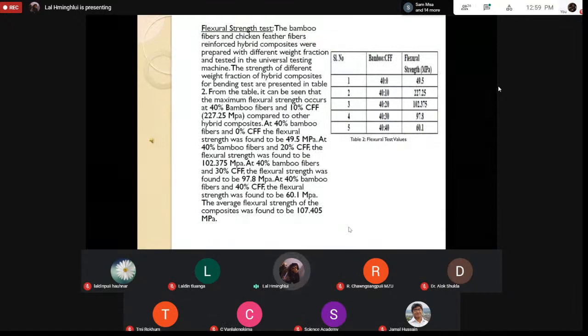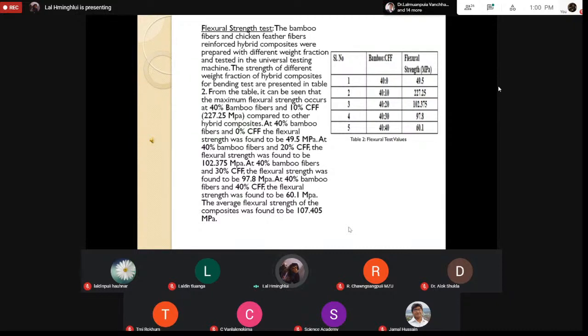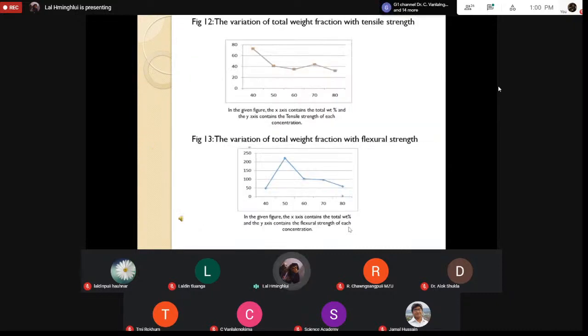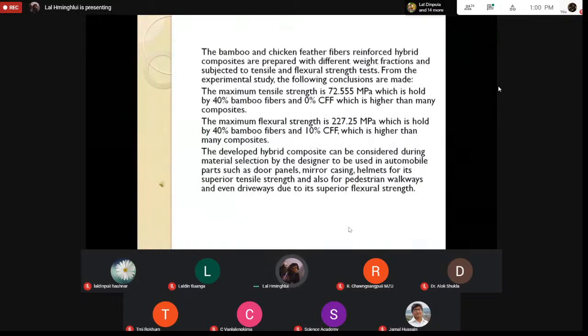And for the flexural strength test, at 40% bamboo fibers and 0% chicken feather fibers, the flexural strength was 49.5. And at 40% bamboo fibers and 10% chicken feather fibers, the flexural strength jumps to 227.25 megapascals. So the average flexural strength of the composites was found to be 107.405 megapascals. In figures 12 and 13, the variation of the total weight fraction with tensile strength is given. In figure 12, the x-axis contains the total weight fraction, and the y-axis contains the tensile strength of each concentration. And in figure 13, the x-axis contains the total weight percent, and the y-axis contains the flexural strength of each concentration.